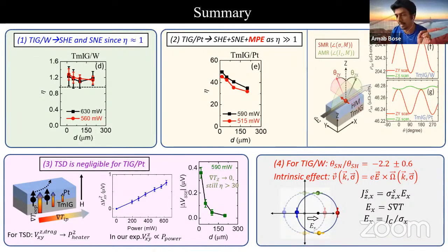And now it doesn't matter. I can apply the same amount of electric field just by applying electric current. So it would also lead to the same amount of spin current. That's what I mean in this case. But again, the numbers are slightly different. If it is 1, then it would exactly mean that, but we are very close to 1, but not exactly equal to 1. So the deviation could be due to the scattering effects.